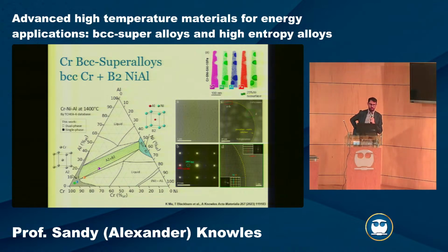So we looked at this topic area of chromium BCC superalloys. It's a similar logic, but now we're taking a BCC metal, chromium, and going across in the phase diagram, we can use the nickel aluminium intermetallic. So now we have a two-phase equilibrium going through that ternary, and we can characterize this. We form precipitates, and this is in SEM. We can form these precipitates, and then we can go into different advanced testing methods.